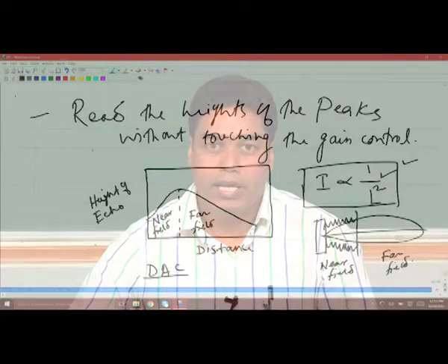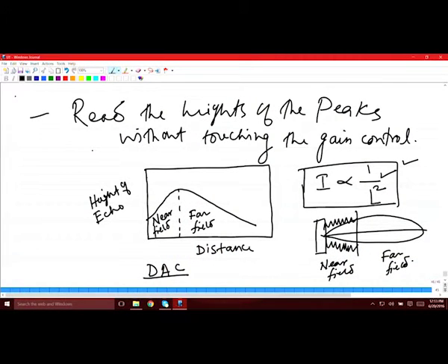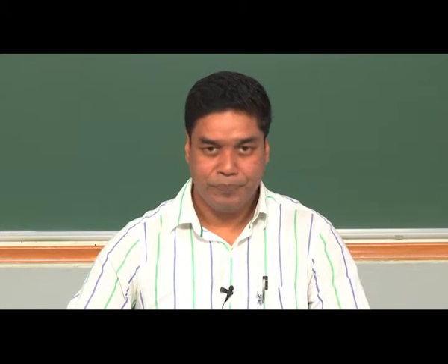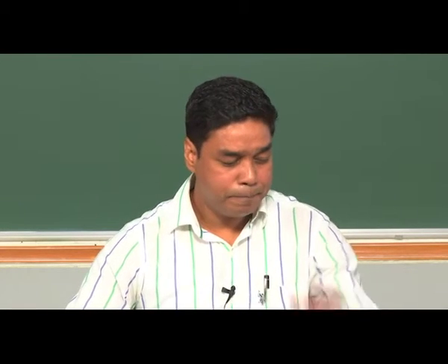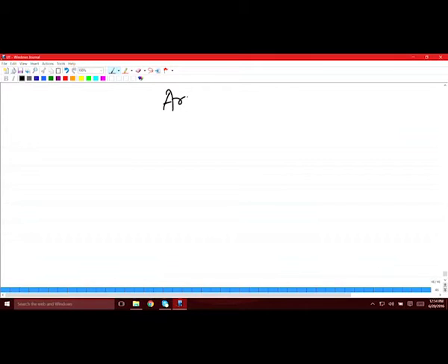Now, let us go ahead and see how the area calibration is done. Okay. So, we could use the same blocks, but for calibrating the area, as I would have said before also, you need to keep the metal distance fixed and you have to vary the size of the hole or the area of the hole. Okay. So, let us see how the area calibration is done.